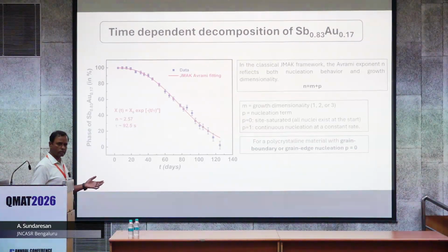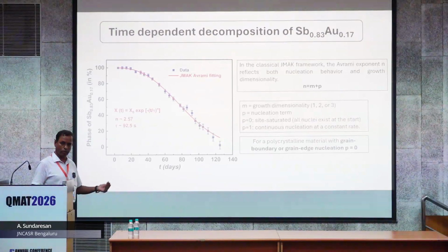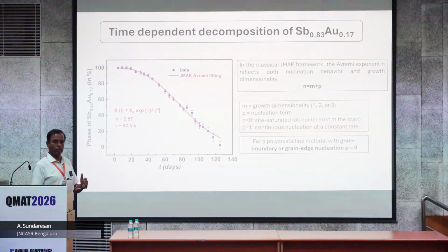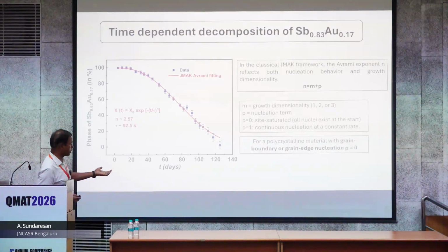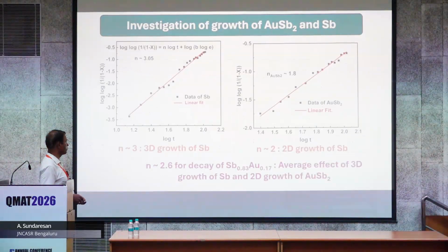This kind of thing - many compounds are not known to exhibit like this. Most of them have large enough barriers or activation energy, so it requires significant time to transform. But this one, within a short span of time, decomposes into almost the starting composition, and we try to analyze it with Avrami fitting and the nucleation and growth of these phases.